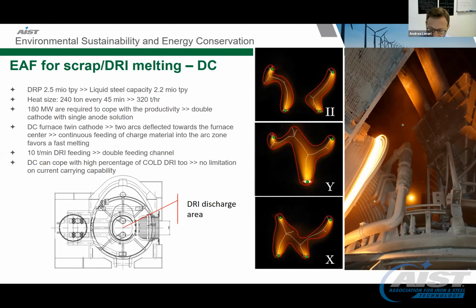This is not possible with a conventional AC furnace, in the sense that the high density zone in an AC furnace is in the middle of the electrodes, which is a very narrow space, very difficult to reach, but it's possible with this configuration. So we can increase the feeding rate of the DRI, we can increase the power density for melting the DRI material, keeping or increasing the productivity. And even in the future, with the introduction also of a relevant portion of cold DRI, these configurations still have, I would say, some safety margin to add even more power, because we have no limitation on the electrodes like we have today on the AC furnace.